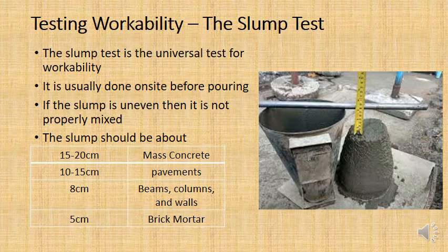With all of the excess water that you're adding, remember you only need about 350 mils of water for every kilogram of cement. Well, the excess water that you add in for workability, that's going to evaporate eventually and create voids in the concrete, and that's going to make the concrete weaker.